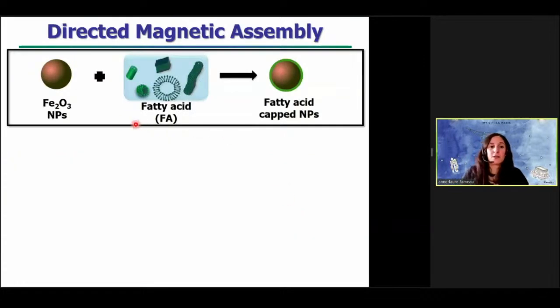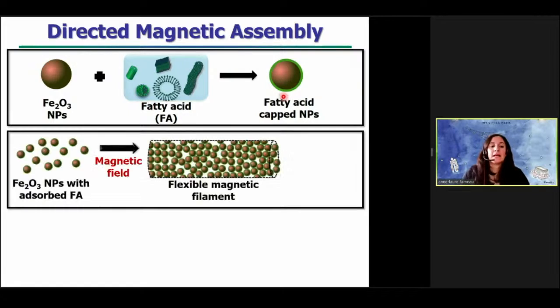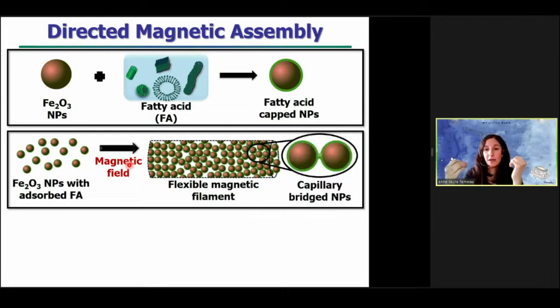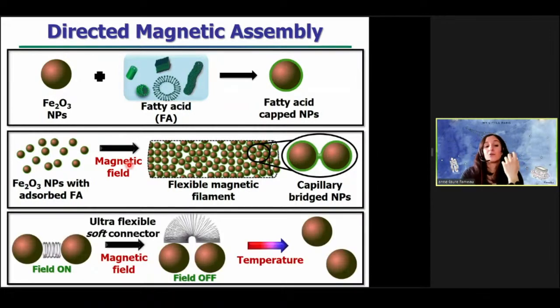So if I summarize, we just use iron oxide nanoparticles, we disperse them in a fatty acid aqueous soap solution, and you obtain fatty acid capped nanoparticles. Then we put these fatty acid capped nanoparticles under a magnetic field like this. And so the magnetic field pulls all the nanoparticles together into microaggregates. When they touch each other, they come into contact, they stick to each other due to the formation of capillary bridges. But what is nice with these capillary bridges based on fatty acid is that they are ultra flexible soft connectors that lead to perfect rollover of the particles, and they are responsive to temperature. So you can form and reform these capillary bridges on demand by tuning the temperature.